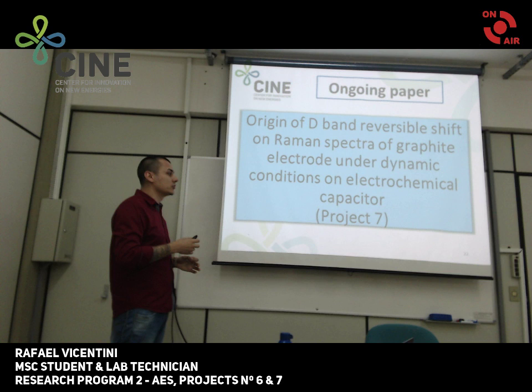Let's look now at some results. As I showed before, this figure shows a schematic representation of the experimental setup used in the Raman operando test. But here, the cell is composed of 2 graphite electrodes separated by a metal porous membrane. In this work, we have been using 4 different lasers: 785 nanometers, 633 nanometers, 540 nanometers, and 488 nanometers. And we have been using these lasers with 4 different electrolytes.